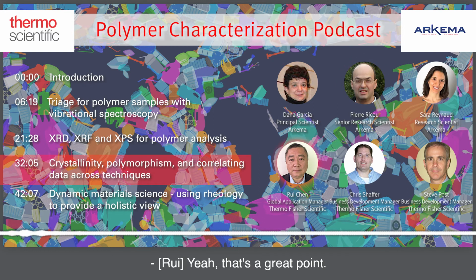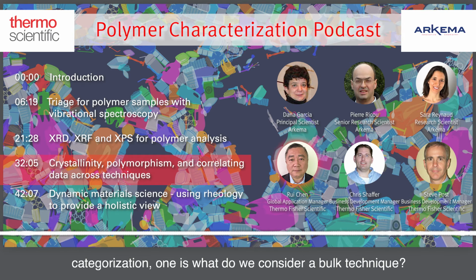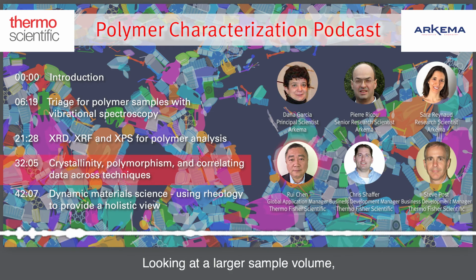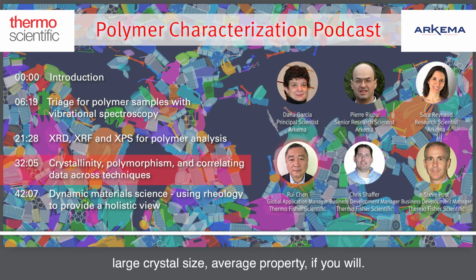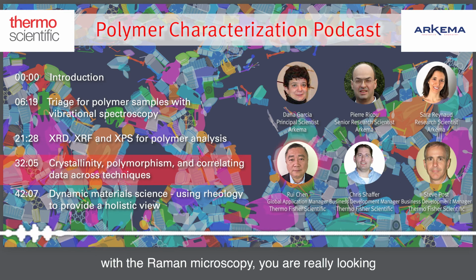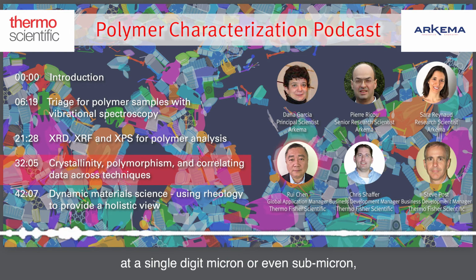Yeah, no, that's a great point. If I'm using a very gross, simplified categorization, one is what do we consider a bulk technique, you're looking at a larger sample volume, large crystal size, average property, if you will. Whereas with Raman, especially Raman microscopy, you are really looking at a single-digit micron or even sub-micron, 750 nanometer, for example. So yeah, that's a very important perspective.